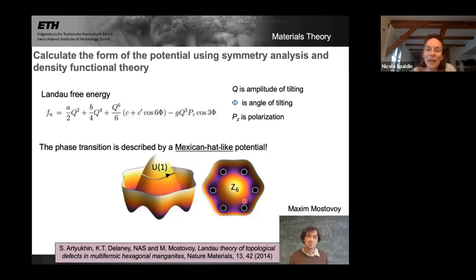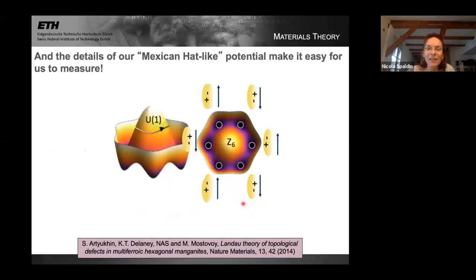There's one big advantage of the fact that we're not perfectly Mexican hat-like. We don't have a perfect Mexican hat, we're only Mexican hat-like. And that's that each of these minima, if we went back to look at the Landau theory, corresponds to an opposite orientation of the electric dipole. So as we cool through our transition at the phase transition region, we have U1 behavior. Down at room temperature where we want to measure, we don't have this continuous symmetry, which would be extremely difficult to measure. We'd just have to measure this delicate evolution of the phase angle of the tilting. But because of the Z6-ness, we're able to instead measure these oppositely oriented ferroelectric dipoles using standard techniques of piezo force microscopy. So in some ways, the fact we deviate from perfect U1 is actually to our advantage.